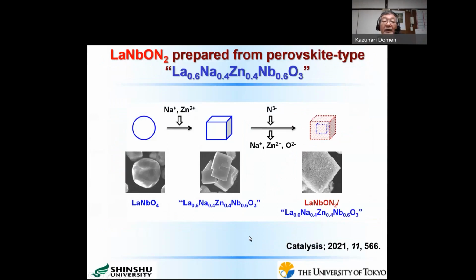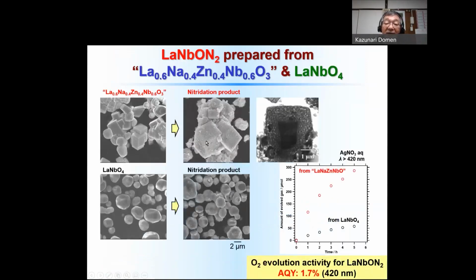Then we further modified our preparation procedure. In this case, we used lanthanum sodium zinc niobium oxide as a precursor material. This is the SEM image of the precursor material. Then we carried out nitridation. As you see here, we obtain a rather porous lanthanum niobium oxide nitride. And these are more high-resolution STEM images. As you see here, the surface region is actually porous lanthanum niobium oxide nitride, but the inside of this material still remains as the oxide material.